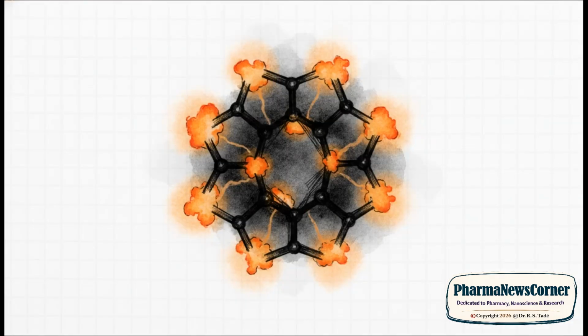But the evolution to brightness doesn't stop there. Notice those surface groups: hydroxyl, carboxyl, carbonyl, and epoxy? By deliberately oxidizing the surface of the GQD, we introduce these functional groups. And what they do is create highly localized defect states directly inside that band gap we just opened up.